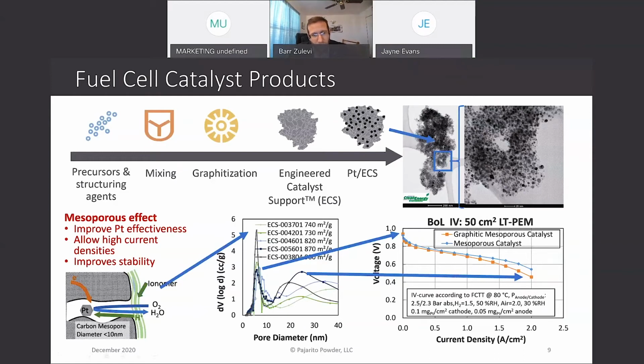We can control some of the pore structures of this, which really help us there. You can see a mixture of small pores in the 7 nanometer range, and then 20 and 30, and that's really the key to the performance improvement of these supports. And then, of course, in this latter stage, we can put platinum on there, which we can see here is really well distributed by this image here by the TEM in the top right. And then we can deploy these in a fuel cell in the bottom right of the image, and you can see really nice high performances.